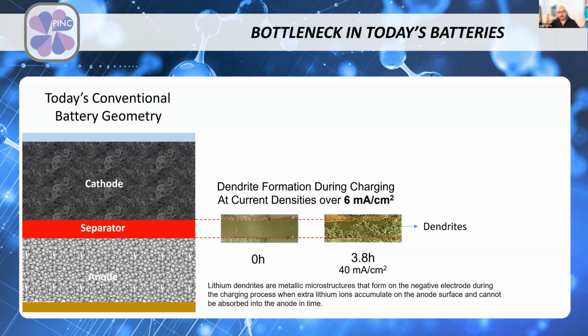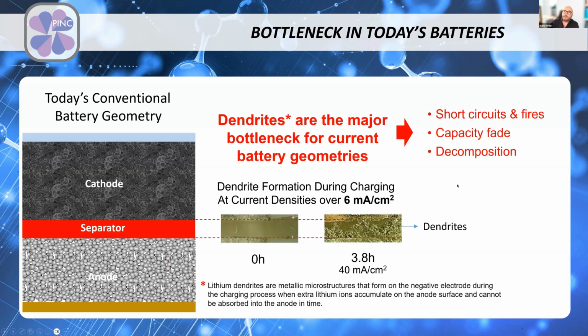All these parameters, the ionic conductivity of the cathode and of the anode, the electronic conductivity of everything, contribute to this problem. So it needs to be balanced quite well. And dendrites being the bottleneck, it affects all the parameters. It affects cycle life, and leads to capacity fade. To reduce these effects, we try to change the chemistries, and the chemistries become even more complex. That leads to side reactions, that leads to precipitation, and it's a chain reaction of events.